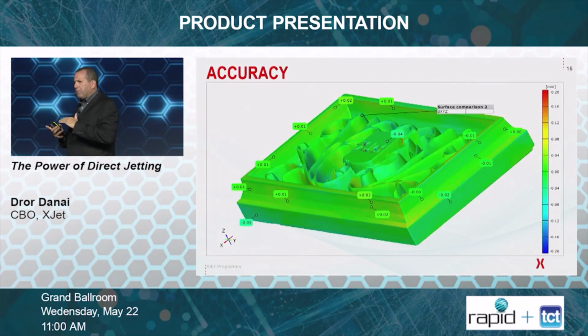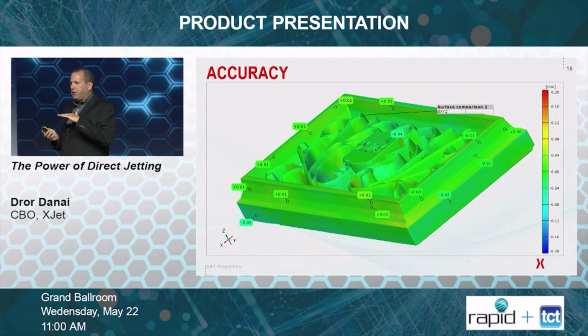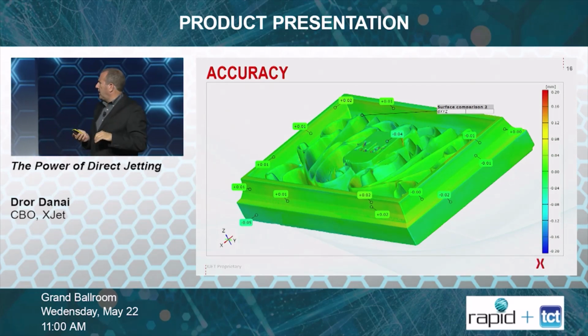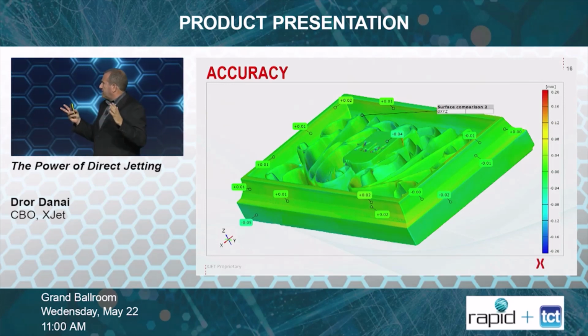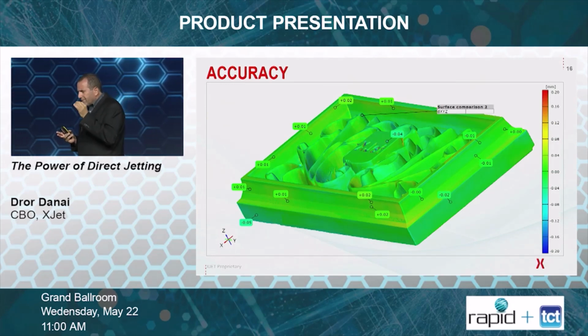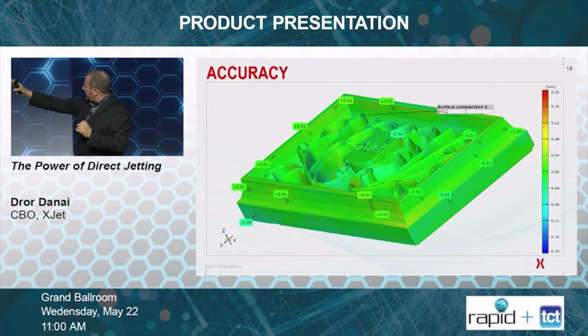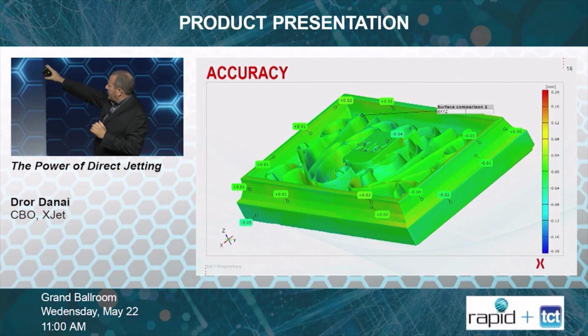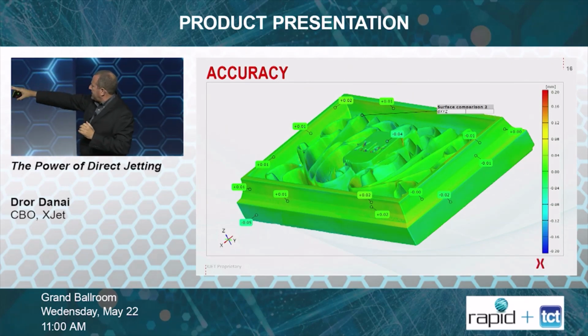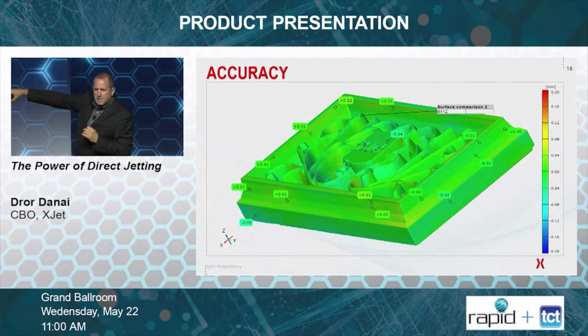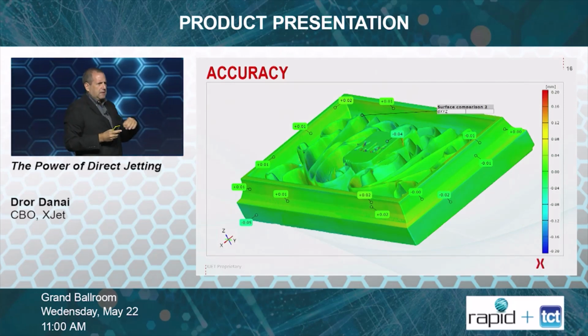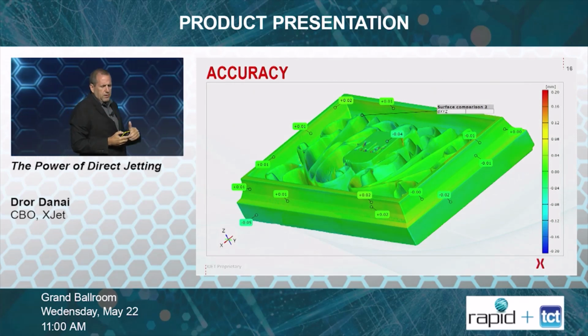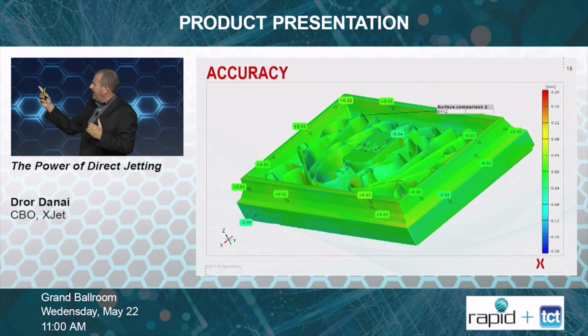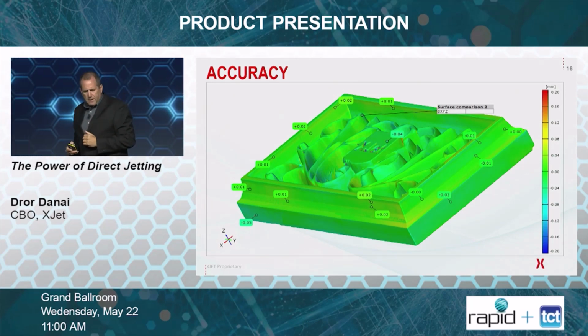Accuracy. We are putting, as you heard, layers of a few microns, so it's very accurate. The system itself is very accurate, and we use nanoparticles. This is a picture from the computer of the accuracy in millimeters. You can look around, you can hardly find any mistake bigger than 50 microns on the bottom left side. So from the exact planned part to the actual part that was printed, the distance is extremely small.